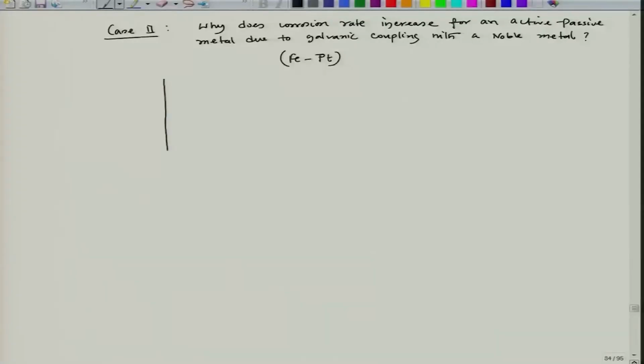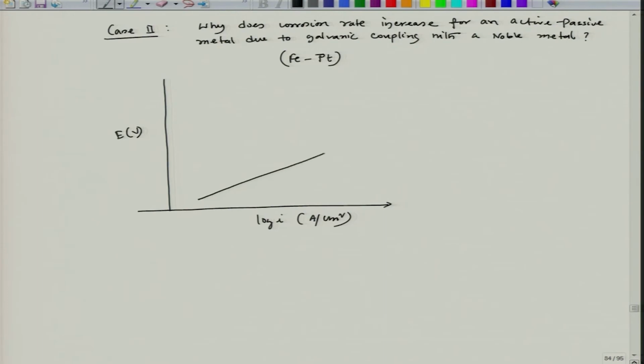Let us draw the mixed potential on this Evans diagram, E volt versus log I, in amperes per centimeter square. Iron is also an active-passive metal, and here the plot looks like this. So this is my E equilibrium with iron, and this is I zero of iron in the acid solution, and this is the passive zone, and this particular point is I critical, and this is I passive.